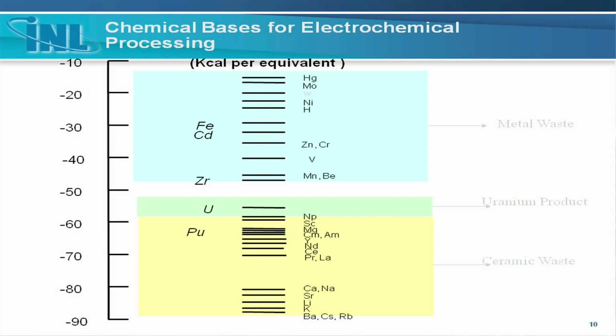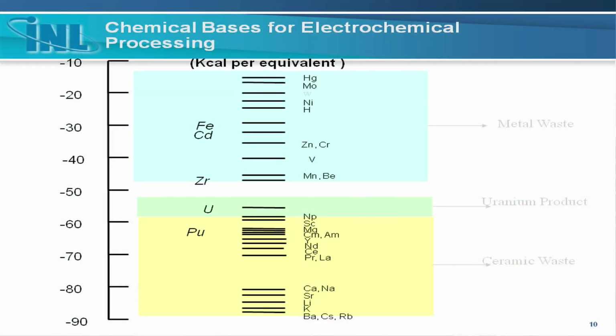These things on the other end of the spectrum, if you dump them in the salt bath, they don't tend to react with the chloride. They're not stable enough, so they'll tend to stay in their zero oxidation state and stay as metals within the spent fuel. And then we can use electrochemistry to separate these types of items into different process streams. So it's these things in the middle here that we can manipulate the process in order to recover them.